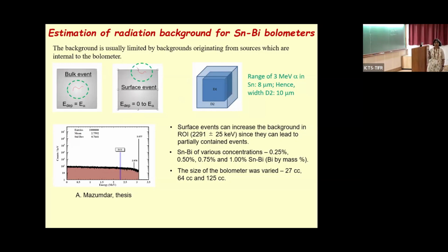Now, in general, not just in tin bismuth, even in most of these detectors, one of the major sources of background, either in germanium or in tellurium detectors, is the surface events, which is illustrated here. Because when you have alpha and betas, alpha particles are decaying, alpha has a unique energy. So why does a 3 MeV alpha become a background for the double beta decay measurement when the region of interest is around 2 MeV?